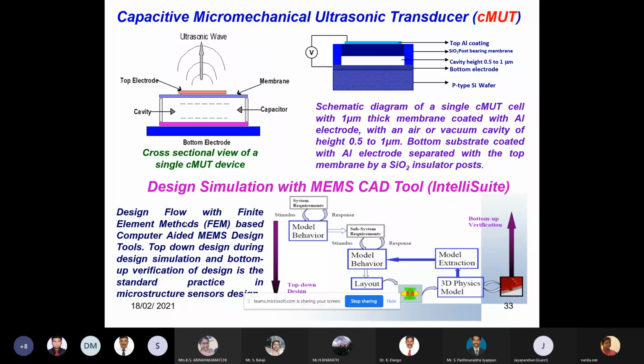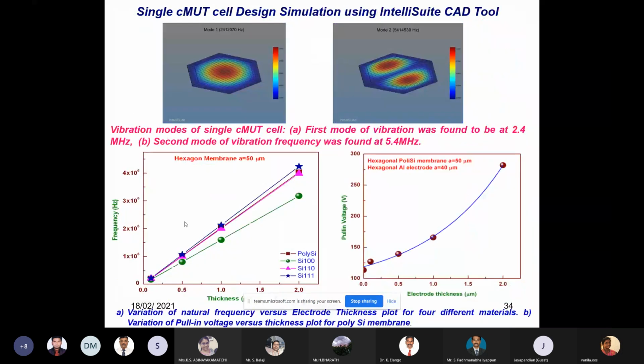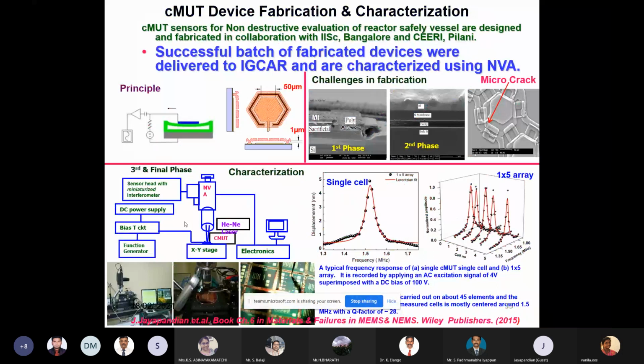For this we used IntelliSuite to design the sensor, and then we fabricated it. This is a simulation result with membrane thickness variation and pull-in voltage monitoring and all, with mode 1, mode 2, which we monitored in the simulation. Then with that we fabricated. We faced a lot of failures, but I am unable to explain now because of shortage of time. We faced a number of iterations, because of failures in chemistry and then in structure patterning. Likewise, we faced a third phase.